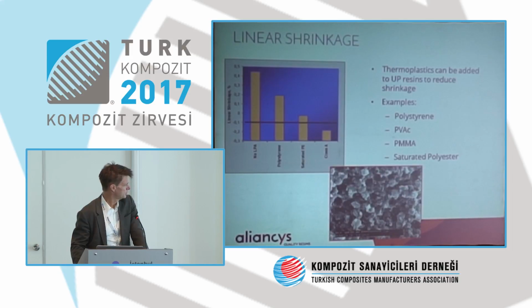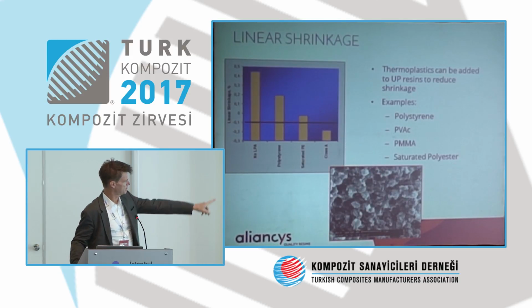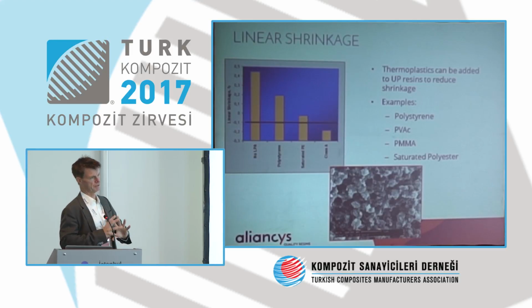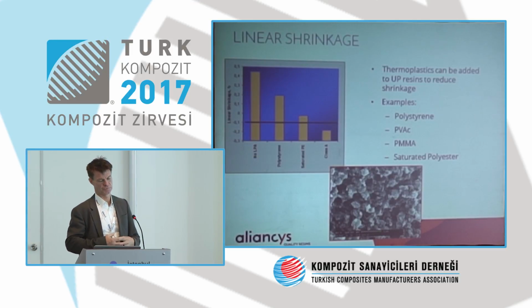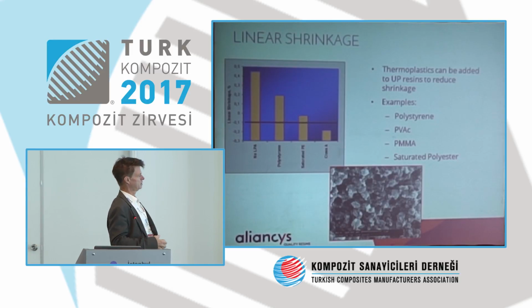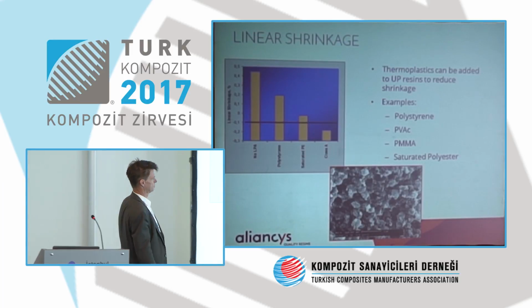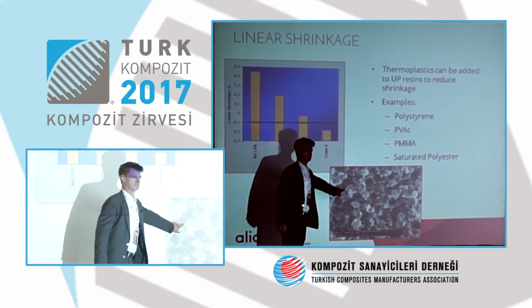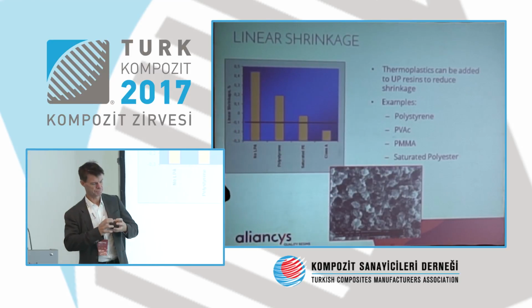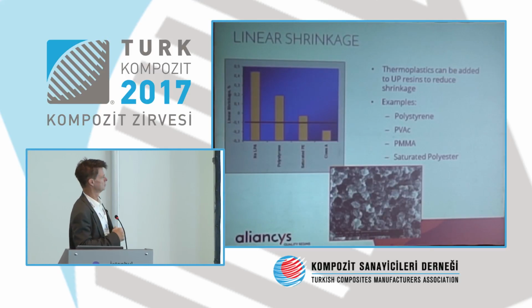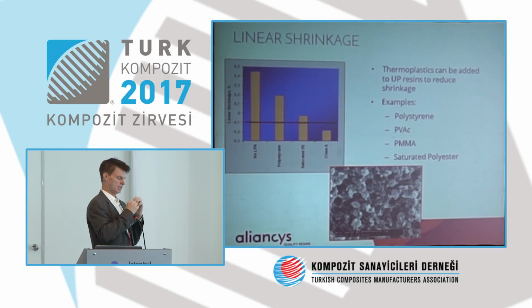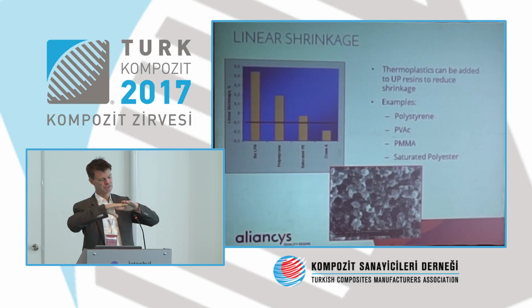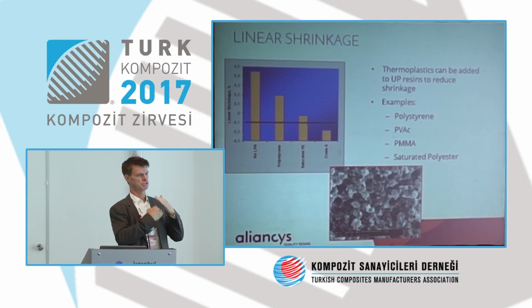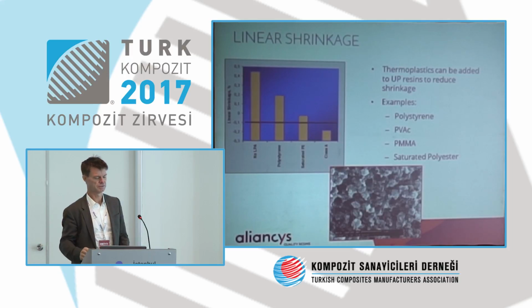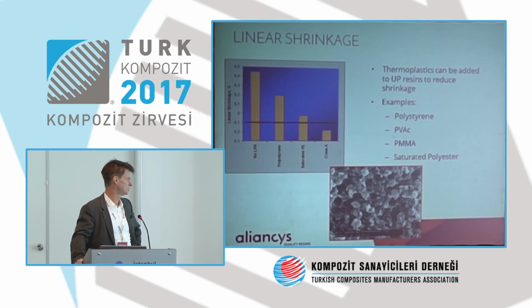And what are we going to do basically with these LPAs inside? We impact the morphology of the material. So we try to gain volume. And if you look at the microscopic picture, this is what is behind. It's a kind of structure where you see some tiny balls, and you have some pressure from the inside of the cavity, and then it will smoothen the surface. If you don't have this pressure from the inside, it will not deliver a good quality at the end.